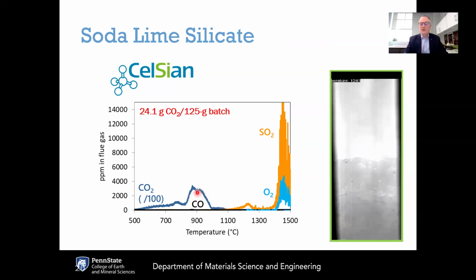released here that predominantly is carbon dioxide, CO2. The dark blue is CO2 concentration divided by 100, and if you integrate that curve, you get over 24 grams of CO2 for this 125-gram batch. At higher temperatures, you're going to see the SO2 blisters being released. This is because of sodium sulfate being used as the fining agent.